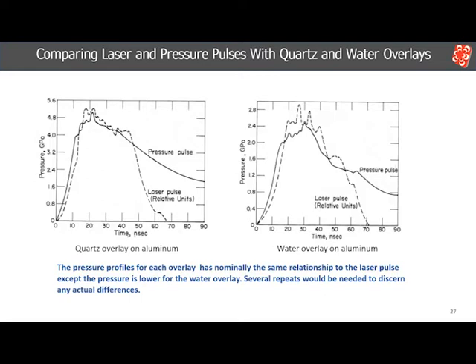Although it was known that water overlays produce lower pressures than quartz, there remained the question of whether there were differences in how the pressure wave developed between the two. To look at this, the relationship between the laser pulse and the resulting pressure pulse was examined for quartz and water on aluminum. The quartz overlay results are on the left and the water results are on the right. As shown here, the pressure pulse has nominally the same relationship to the laser pulse for both overlays.